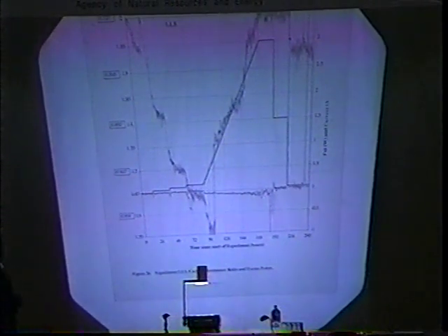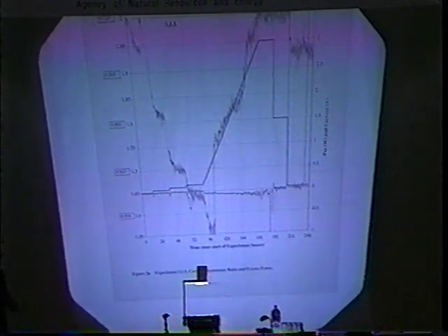As you can see, for those of you who are very familiar with this, the cathode was deloading at open circuit. As we turned on the current, it loaded, went up over the resistance maximum, 0.727, and loaded again to a final loading level of about 0.96. Again, a spectacular value. But as we began to increase the current, hoping to produce excess power, very shortly in the current ramp, the cathode simply deloaded.